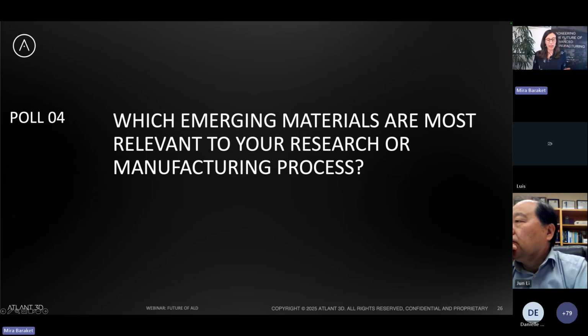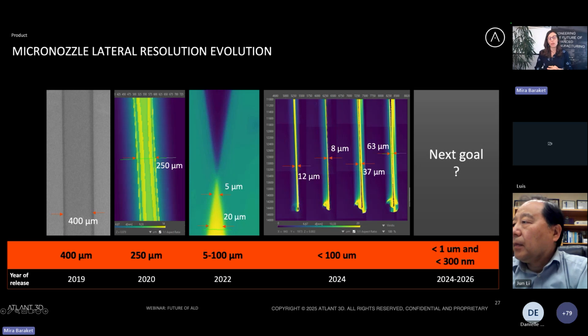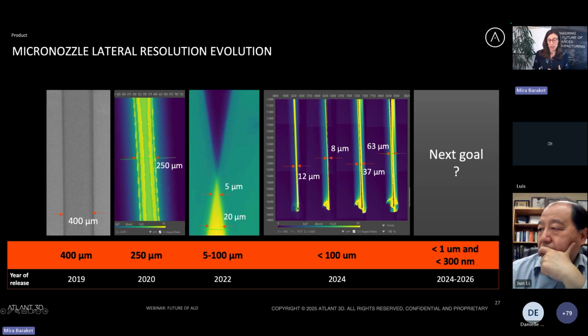All right, so this brings me to my next topic, which is about the resolution size that we are able to achieve. In 2019, when the technology had proven its first proof of concept, it was done with a 400 micrometer lateral size resolution. So our nozzles, as I mentioned earlier, are customizable. And then we made some progress, and in 2020, we were able to achieve 250 micron. And then with different processes and understanding of our process, we were able in 2022 to introduce a few steps that allowed us to go as low as 5 micron in deposition resolution.